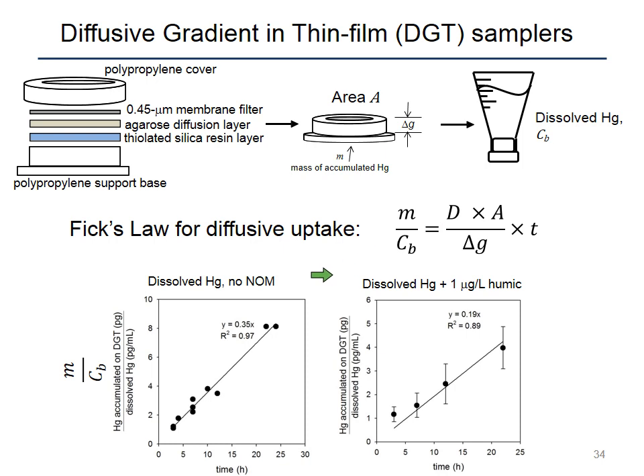So on the left is a solution with just dissolved mercury, so mercury as a mercury hydroxide complex. On the right, we also have humic acid, so this mercury would be complexed by humic acid. And we also see a linear uptake in which the slope is smaller than on the left, and that could be explained by a smaller diffusion coefficient of mercury organic matter complexes in this resin layer relative to mercury hydroxide complexes. So this seems to work when you have only dissolved species of mercury in solution.